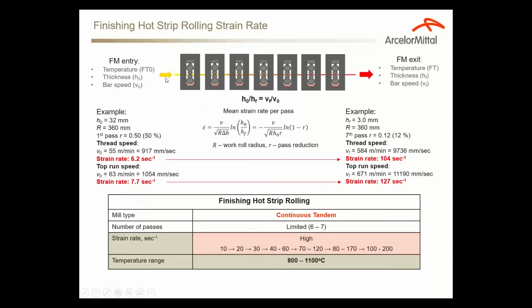Of course, when the speed of the bar going through the mill changes this way, it does change the strain rate at which the steel is deformed. And here are some examples of how the strain rate changes depending on the entry thickness and the final thickness of the strip. This example gives you an idea. It's basically an order of magnitude increase in strain rate. And you can see how the strain rate can change depending on the final thickness of the bar. Just giving you an idea of the orders of magnitude that the mill sees in terms of strain rate.